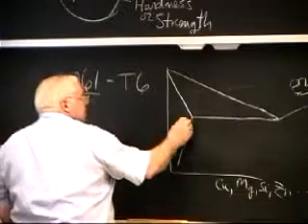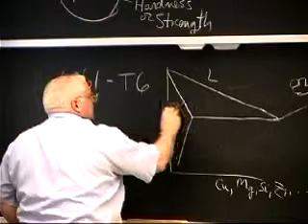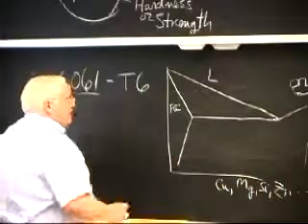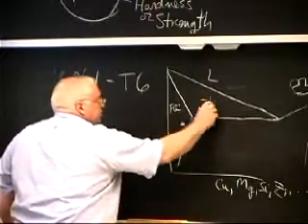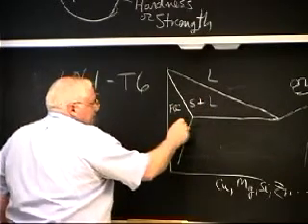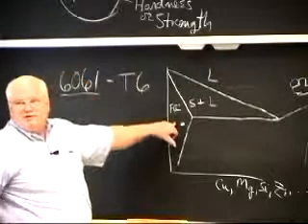If I heat this, this is liquid, this is solid, face-centered cubic aluminum, and then I'll have some precipitate over here, which might be aluminum copper, aluminum magnesium, or aluminum silicon, intermetallic. If I heat it up to this temperature range, this is liquid plus solid here, and this is solid, I'm still in the solid range, I can dissolve everything into single phase.